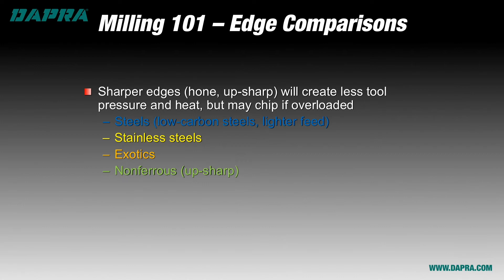For very challenging materials like titanium, Inconel, and high temperature alloys, the use of a honed edge provides the shear that's necessary to help prevent built-up edge and heat, both of which are significant difficulties in these materials. On non-ferrous materials like aluminum, plastics, composites, and wood, an up-sharp cutting edge usually provides the best results. However, given the abrasiveness of many composites, some form of wear protection such as coating or diamond tipping may be necessary.